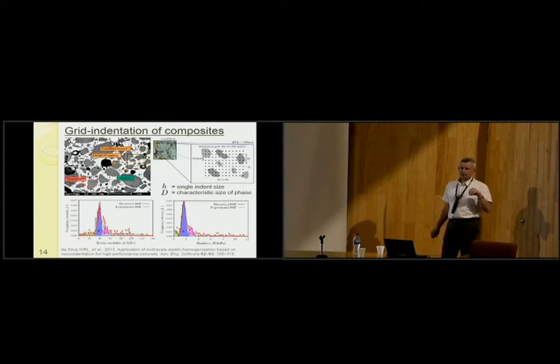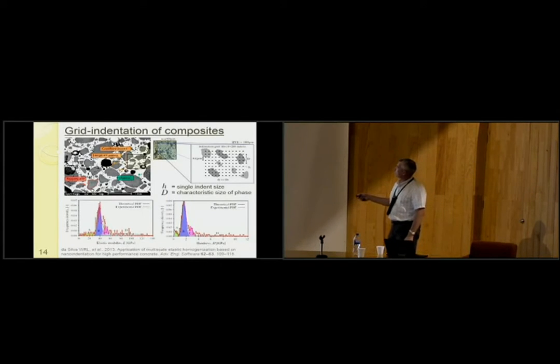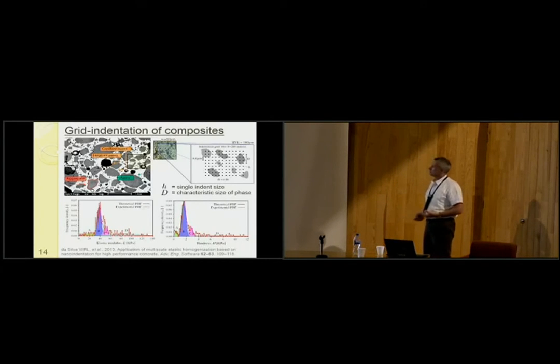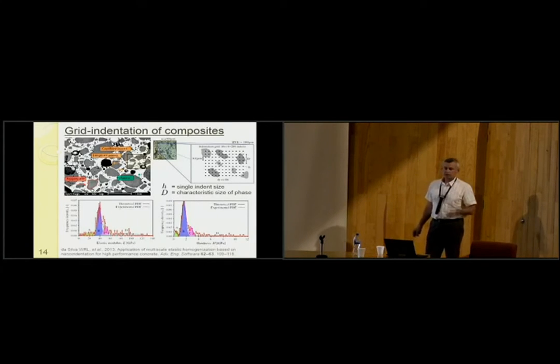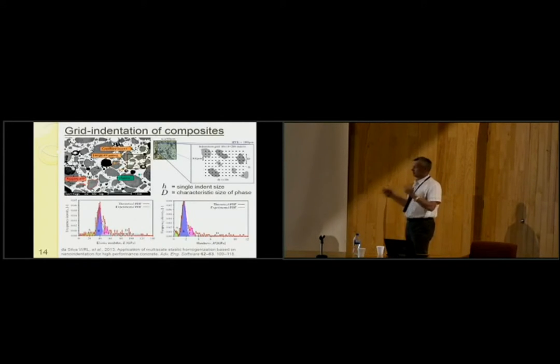So these triangles show indents of indenter pyramid, and making indentation, we can measure incremental indentation stiffness. However, when we move across the surface, we obtain different values, and this is due to the fact that properties of the material change. So, we have measured data about indentation, and now the question is how we can extract properties of composite materials.